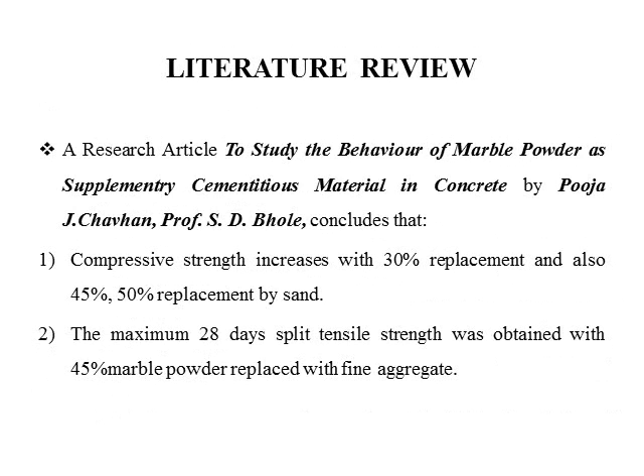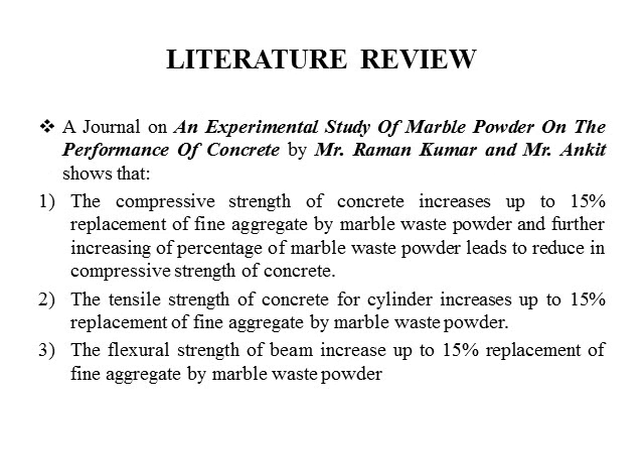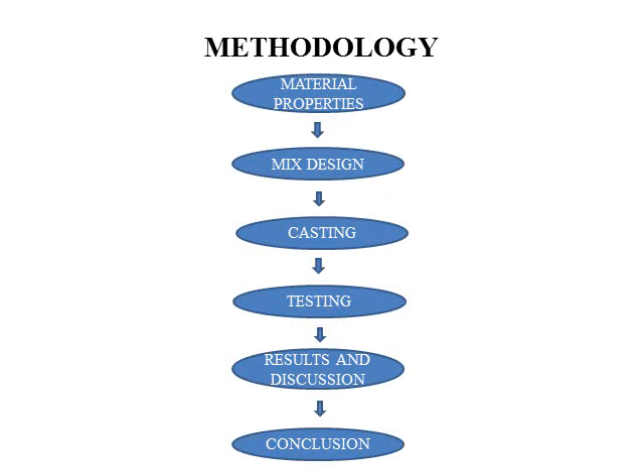The split tensile strength increases from 3 to 41% with addition of steel fibers. A study of the behavior of marble powder as supplementary cementitious material in concrete concludes that compressive strength increases with 30% replacement, and also with 45% and 50% replacement of sand. A journal on an experimental study of marble powder on the performance of concrete reports that the compressive strength of concrete increases up to 15% replacement of fine aggregate. The tensile strength of concrete for cylinder increases up to 15% replacement for fine aggregate. The flexural strength of beam increases up to 15% replacement of fine aggregate with marble waste powder.